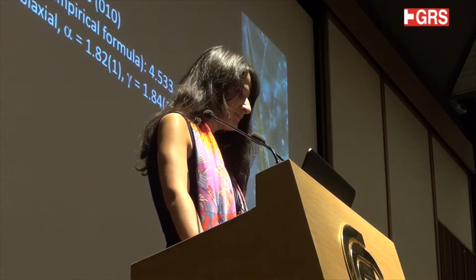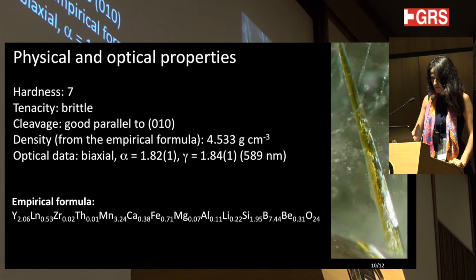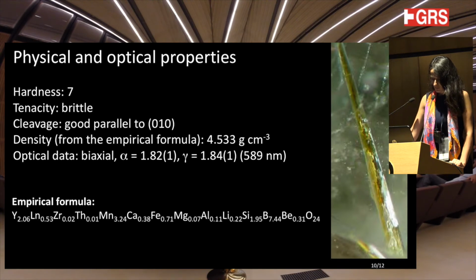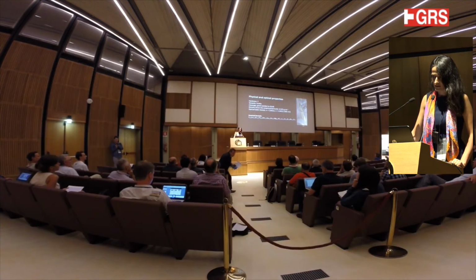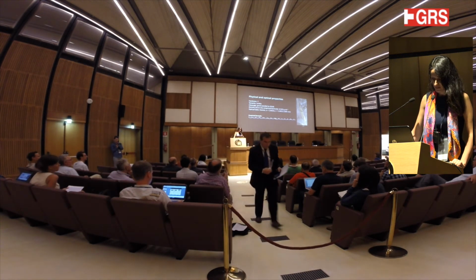Just to make a short summary of the physical and optical properties, perettiite is brittle with hardness around 7. The cleavage is good parallel to 010. We calculated the density from the empirical formula, and it was 4.533 grams per cubic centimeter. Concerning the optical data, perettiite is biaxial, but we had serious problems because of twinning, so it looks conoscopically uniaxial. So the data that you see, the alpha and gamma, should be interpreted as a maximum and a minimum of the refractive indices.